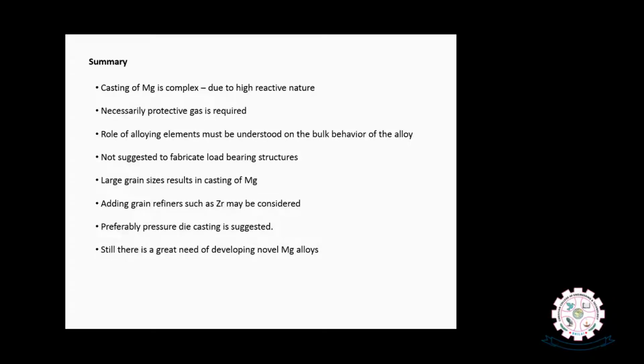Adding grain refiners such as zirconium may be considered to decrease the grain size and grain growth. Preferably, pressure die casting is suggested, which produces an advantage with grain-refined structures, like what we produce from squeeze casting. Still, there is a great need for developing new magnesium alloys since the area is evolving to new levels. Development of new magnesium alloys is still challenging, and there is a lot of promise in research areas of developing new magnesium alloys.